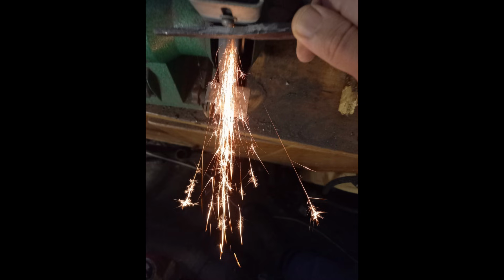In contrast, iron produced from bog ore, as many other countries had to rely on, is very difficult to turn into a steel, as the phosphorus will inhibit carbon migration and will actually push out a little bit of the carbon once it is there in the steel, making it very hard to use as a source for swords. In contrast, iron made from roestone will already absorb enough carbon during the refinement stage of folding and welding to be considered a hardenable steel, although of low to medium carbon levels.